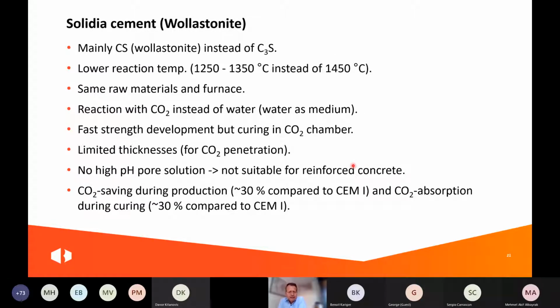Solidia cement is another interesting alternative. It's a product of LafargeHolcim. It's basically wollastonite. Wollastonite is calcium silicate, so CS instead of the C3S, and it has to react with CO2. That limits the sizes of the products, so you cannot process it like regular concrete. You have to produce relatively small products and then store them for 24 hours in a CO2 chamber in order to let it react. But then you have a very quick strength development, so it is interesting, especially for unreinforced applications.